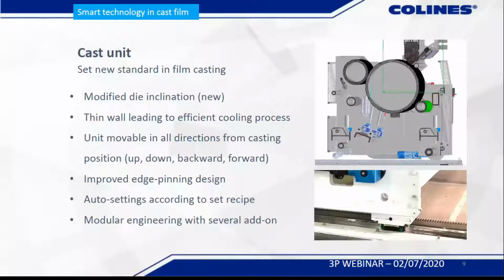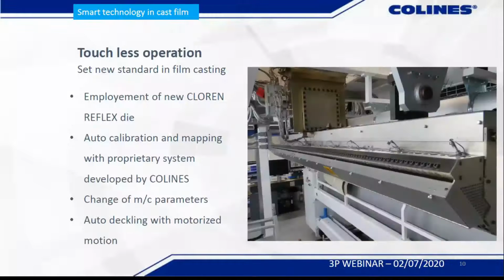About the touchless operation, basically we use the new Cloren Reflex die, providing superior control over the thickness tolerance. What we have done, we have developed a software cooperating the measuring unit and the die. That basically, in 2 minutes we can go to 2 sigma 0.2, even with big lines. So also change of the thickness and especially startup of the machine now requires, let's say, 1/5 of the scraps that were collected before. There is also the option for making the deckling with motorized motion, so the lines then become really touchless.